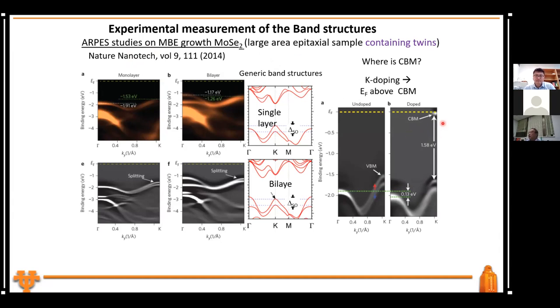So then they see, wow, the band gap is only 1.5 eV in MoSe2, while the optical transition is 1.65 eV. You cannot have negative exciton binding energy. So that really gave rise to this first very intriguing phenomenon in 2D.